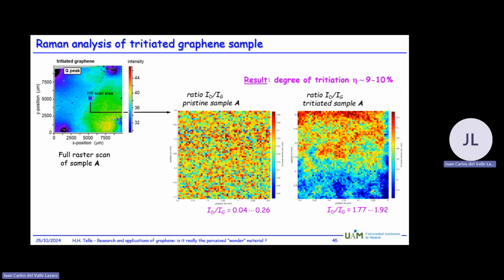Helmut, I was wondering, related to the question, how do you calibrate the efficiency rate? Again, for hydrogen we have not done this, but other groups have. With tritium, we have done that ourselves: at the end, you heat your sample up so that everything comes off. Then you can calculate from the amount of pressure how many particles there are, and that is the amount of tritium absorbed on the sample, or hydrogen, or whatever else you have. You have to ensure at the very end that you dissolve everything and can measure it with high precision. And for many molecules, there are procedures to quantify them.